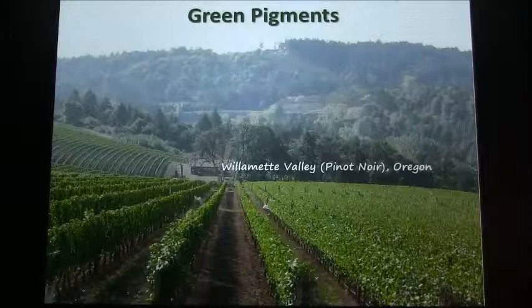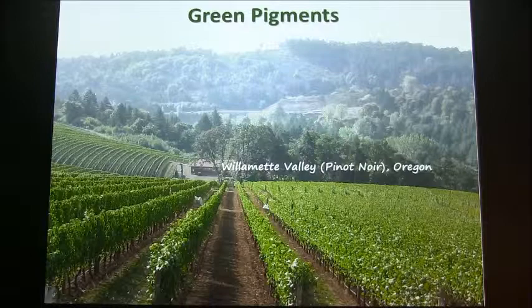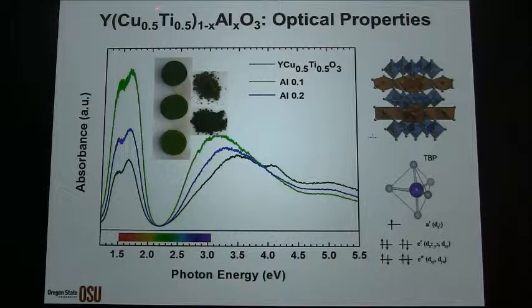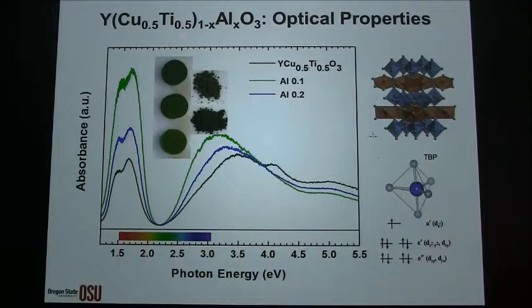We can also create green pigments. Green pigments are again harder to make, but what we did was, instead of manganese, we actually took both indium and manganese out. We replaced the manganese and indium by copper and titanium. Copper is 2+ and titanium is 4+. The manganese there is 3+. So we mimic the same composition, same crystal structure, but you get a 5-fold coordination where you put copper and titanium. Now we can create a green pigment.